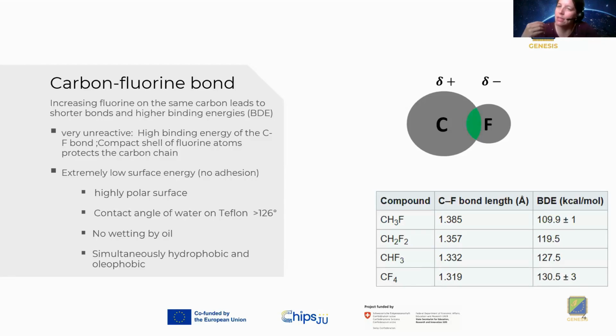So basically that means the more fluorine you have there, the shorter the bonds are. The more hydrogen you substitute by fluorine, the shorter the bonds. The more fluorine you have, the more stable your compound is. This is given by the binding energy in the last column. You can also see that this is increasing with the amount of fluorine you have.